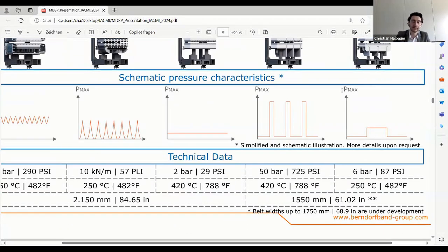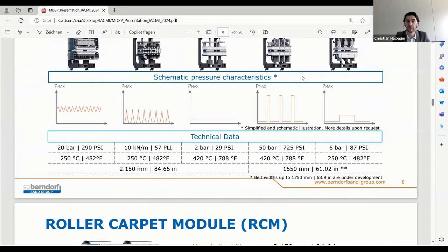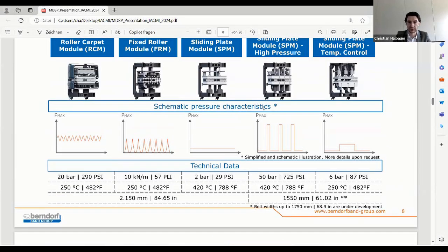In general, we do have different options for heating and cooling our models. Our models can be either heated by thermo oil. In that case, they can go up to 250 degrees temperature, which is 482 in Fahrenheit. Or we can also use electric heating rods, and then we can achieve higher temperatures of up to 420 degrees with a pressure level of up to 50 bars in case of the high pressure model, which gives you like 725 psi in pressure.